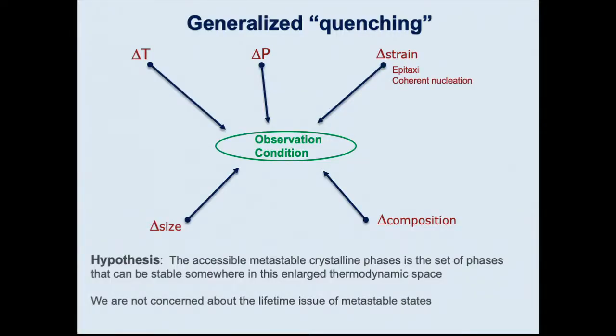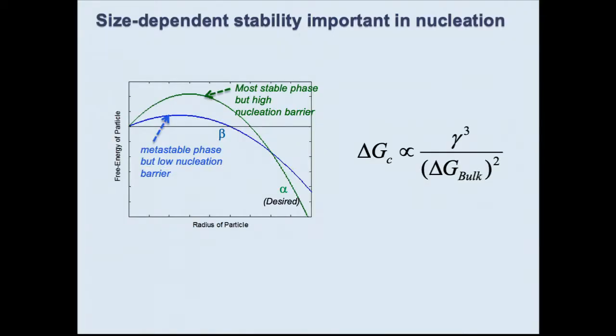Okay, so the one that's maybe more interesting is size. And the reason is that we already, I think, also believe to some extent that size matters because nucleation preference is set at a small size. So, for example, if you look at two nucleation curves, right? This is a classic out of materials science. You look at free energy of transformation as a function of the particle size that's forming. And here I've taken a case where green is the stable phase because at large particle size, it has the lowest free energy. But beta has higher free energy in the bulk, but it has a lower nucleation barrier. So in this case, you will form beta first.